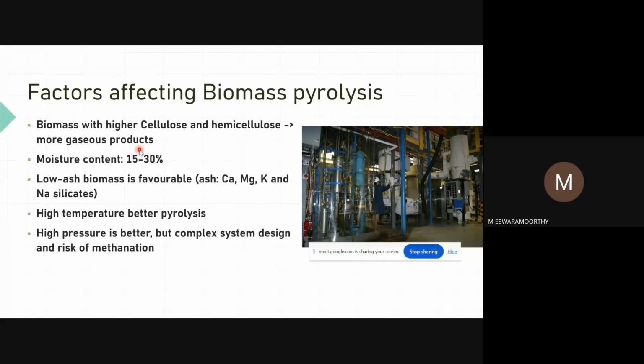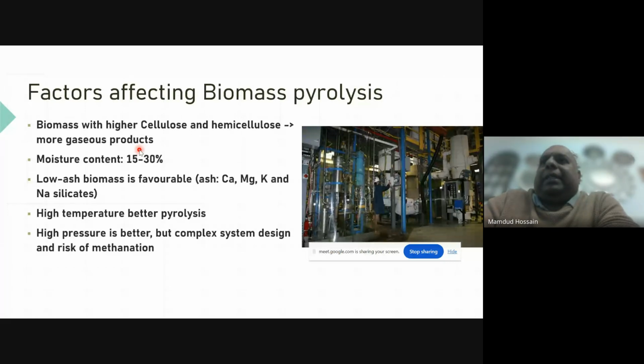Okay, so what are the parameters that impact biomass pyrolysis? The main impact is that we need biomass with higher cellulose material, so then we can get a higher gaseous product. Moisture content should not be more than 30%. Low ash biomass is favorable because, as I said, of char formation and things like that. High temperature, of course, gives better pyrolysis. High pressure is also better, but then you need a complex system design. And at high temperature, there is more risk of producing methane rather than hydrogen. The methanation reaction can happen at high temperature and high pressure.